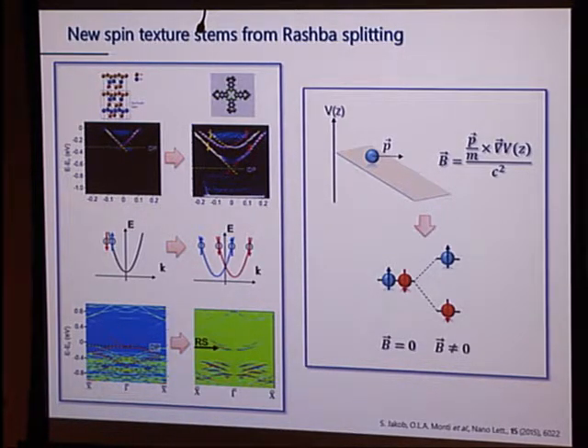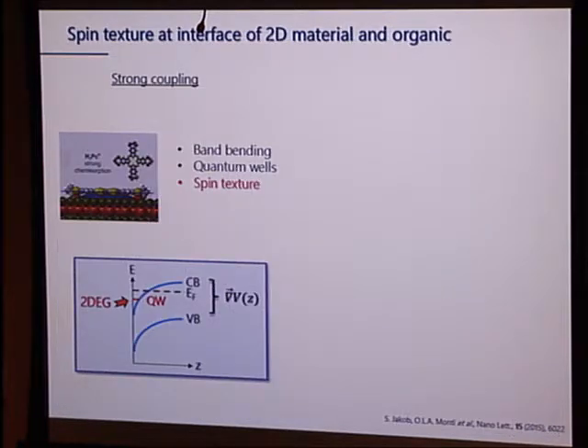So as we measure the band structure in the Brillouin zone, we know that we can go from gamma to plus X or gamma to minus X. Those are two different momenta, and this is how we measure. This is what we get from the experiment. So the question is, what is this potential gradient here? Well, if we look carefully, what we see is that there's actually quite enormous band bending. Band bending just means that when you have charges at the surface, those do not get properly screened. This then induces an extra electric field, which will now need to be added to the energy of the conduction band and the valence band.